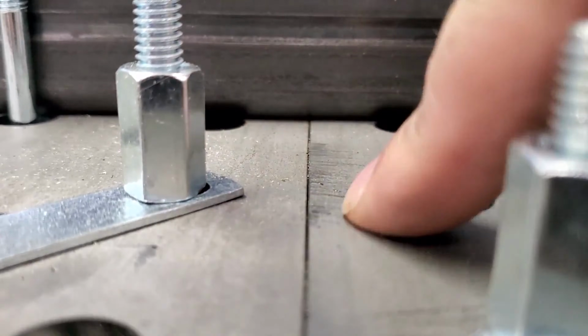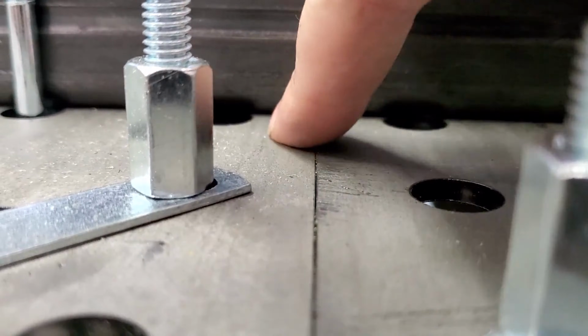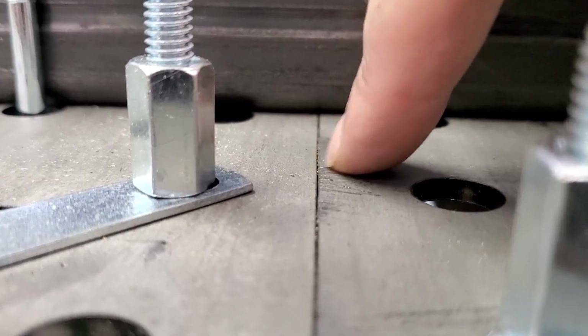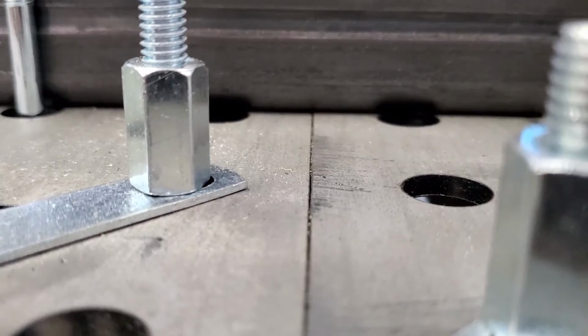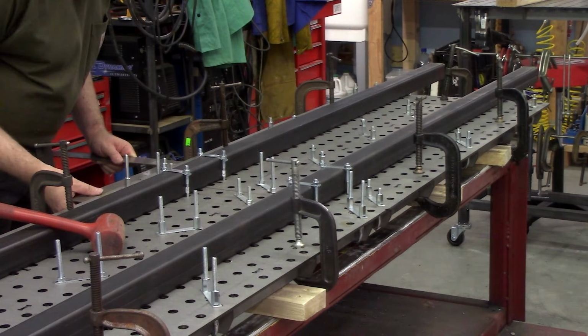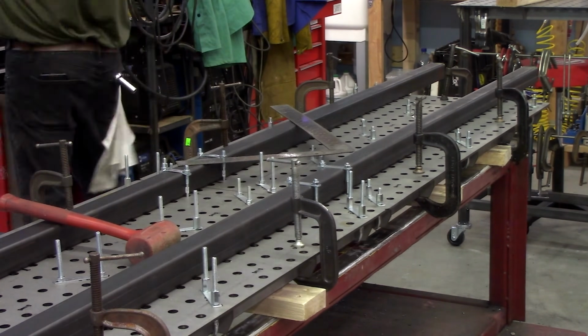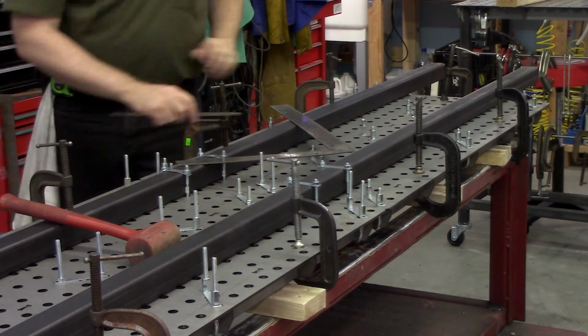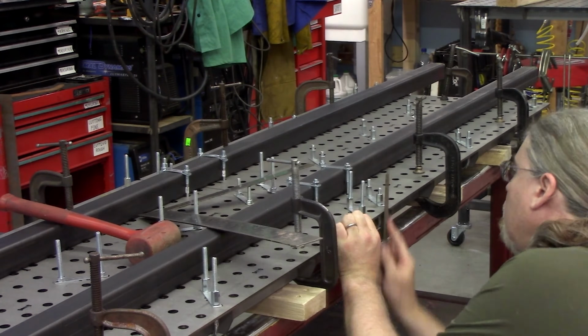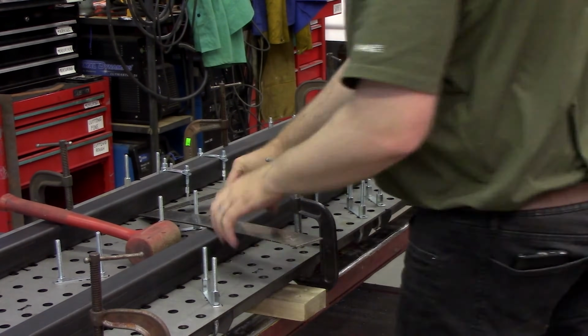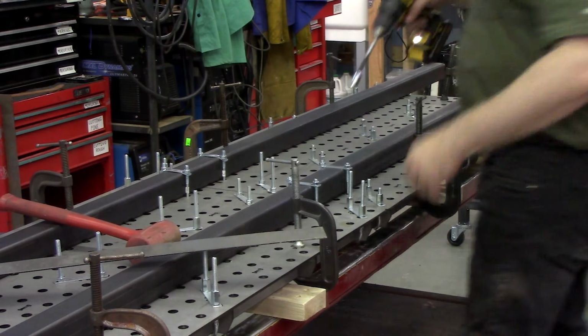Along most of the center where the two tables joined, I couldn't feel any difference in height dragging my fingernail along in either direction. In some spots I could catch it though. These were not more than 2 or 3 thousandths off, and I would just hit them with the flapper disc later. Overall, the alignment looks really good. Even the side-to-side alignment looks good. I triple-checked the alignment, filing off some small nubs left over from the laser cutting process to check the side-to-side alignment, and then tightened the other main center bar that connected the two tabletops.